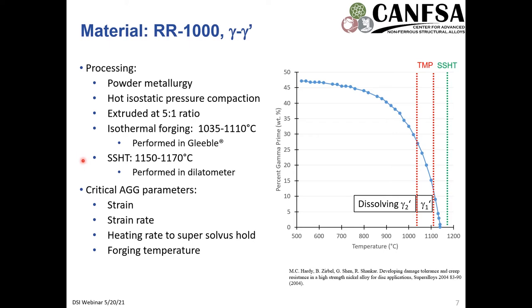And after the isothermal forging, there's a super solvus heat treatment that was performed at 1150 to 1170 Celsius. And I utilized the quench dilatometer for this, mostly for the precise time and temperature control. And here on the right plot, we have the phase fraction of the gamma prime versus temperature. And we see that at these lower temperatures, we're really dissolving just the secondary gamma prime within this thermomechanical process, our TMP regime. We're starting to dissolve the primary gamma prime. And as we approach the super solvus heat treatment temperature, we have all of the gamma prime dissolved.